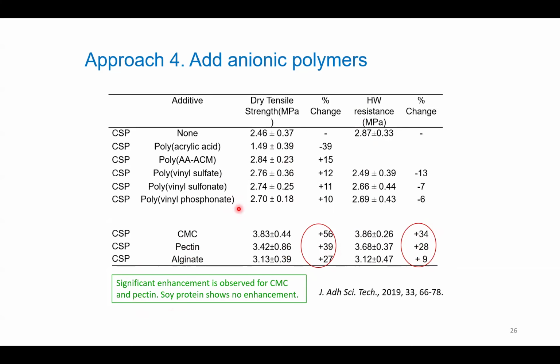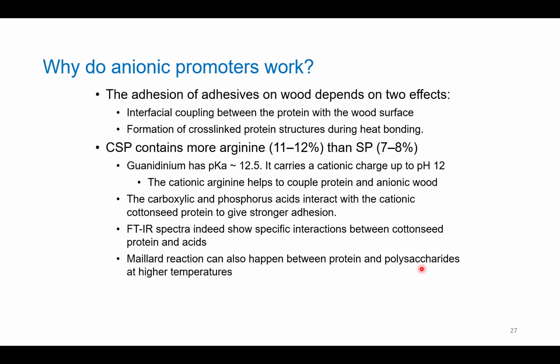Now, what's interesting is that this only works for cottonseed protein. If you use soy protein, it shows no enhancement. So the question is why? Now, we know the adhesion of adhesives on wood depends on two effects: interfacial coupling between the protein and the wood surface, and the formation of cross-linked protein structures during heat bonding.